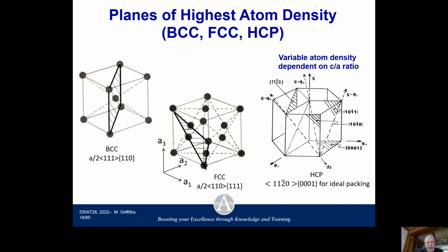You get most action related to that higher density of plane. However, when you move to zirconium and titanium, for instance, these pyramidal and prismatic planes become the dominant plane because they actually end up being the higher density of planes, even though they are corrugated. But again, I don't need to get into that for the sake of this particular discussion.